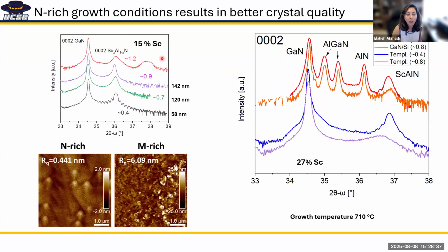We have also then looked at nitrogen rich versus metal rich. And by that, what I mean is that in MBE, the gallium nitride growth is always metal rich, meaning that the gallium flux is more than the active nitrogen. But what we have seen is that for scandium nitride, when we grow nitrogen rich, meaning the total metal flux is lower than the active nitrogen, we can get better surface morphology. And we have seen this both on GaN on sapphire and GaN on silicon, that when we do nitrogen polar, nitrogen rich, the peak from X-ray is better defined, which shows the higher quality of the crystal.